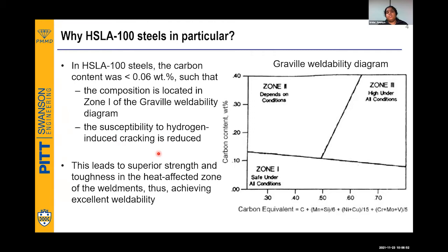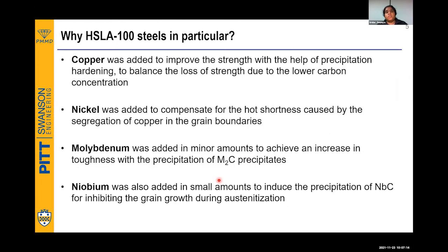Now, we all know that the weldability is mainly evaluated based on how strong your heat affected zone is, because the heat affected zone is the first one which is going to fail in a weldment. So the point here is this: we are improving the weldability by improving the strength and toughness of the heat affected zone. Okay. Now, one problem solved. We have reduced the carbon content, but we all know that carbon is the main strengthening element in steels, and we are going to reduce it. And how are we going to compensate for that?